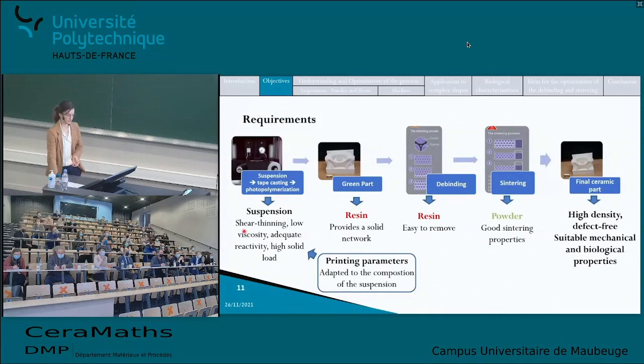The resin has to provide a solid polymer network because we want to be able to handle the green parts, and it also has to be easy to remove in order to avoid the appearance of cracks during the debinding. Finally, the powder has to have good sintering properties, in order to obtain a final ceramic part with a high density that is defect-free and that has suitable mechanical and biological properties.